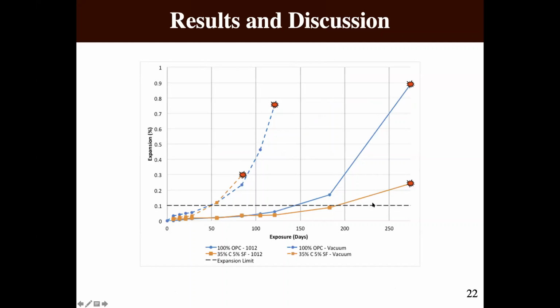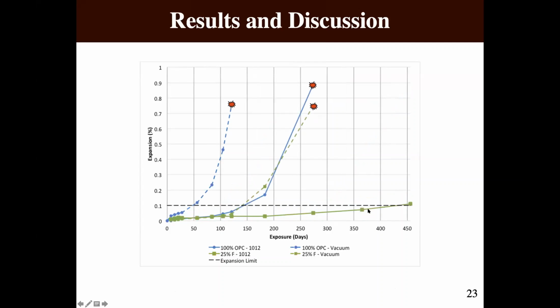When looking at the ternary system, now you see an even more dramatic increase again, and then even more in the case of the Class F fly ash. So the Class F fly ash, while it didn't necessarily exceed the expansion limit until about 15 months in this case, for the vacuum saturation method you had about more or less 6 months in terms of when that exceeded the expansion limit, right?